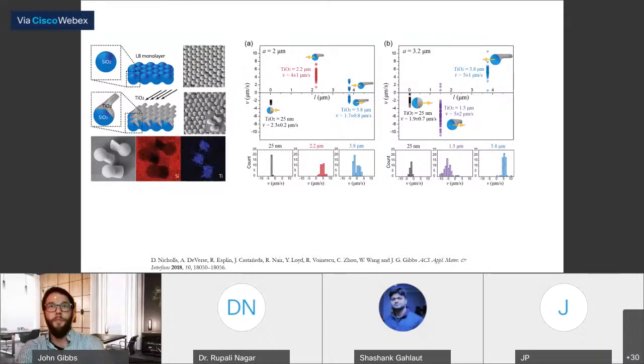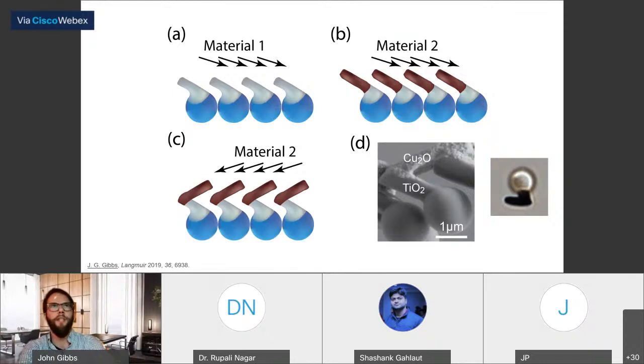Okay. So we want to take this a step further, and really what the idea was for this project is we wanted to use multiple photocatalysts that have different band gaps, so energy band gaps. And what we were trying to go for is to be able to use two different colors of light, right? So we already know that TiO2 is going to be activated under ultraviolet light, but we looked for a bunch of different types of photocatalysts that are going to be active in the visible range too. So the one that we ended up falling on is copper oxide, so Cu2O.